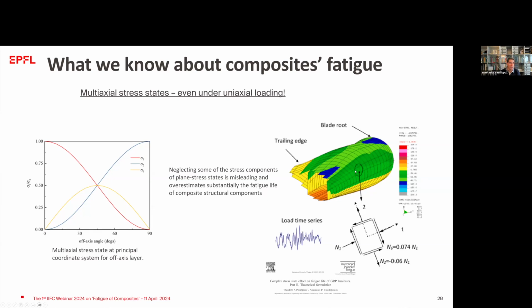Until more or less 2000, the main stress component that was used for design was the sigma-1, so the normal stress. We have shown that even if you have very small sigma-2, so normal stress in the other direction, and sigma-6, the shear stress, that are very few compared to the sigma-1, these components can still give significant effects to the failure of the material. So it was necessary to consider all the stress components for designing composites in fatigue.